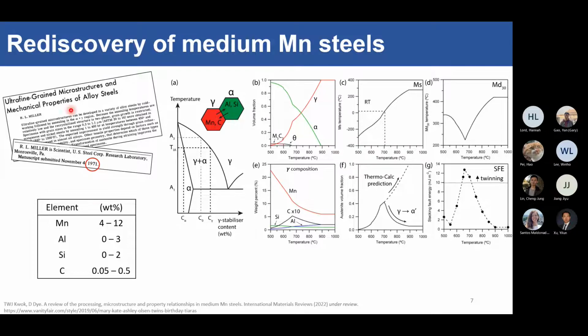So if you take your steel and you heat it into the two-phase regime here, what happens is that your manganese and carbon partition into the austenite, aluminum and silicon partition into the ferrite phase. And you hope that you can actually enrich the austenite phase in manganese and carbon such that it's at a sufficiently high level to enable twinning. So you can actually simulate this in Thermo-Calc. You can plot the phase fraction evolution with temperature, and then you can plot the austenite composition with temperature, and then you can plot the change in stacking fault energy with temperature. So what this means is that if you do an intercritical annealing heat treatment between 650 to 750, you might have your stacking fault energy just high enough to enable twinning in this particular steel.